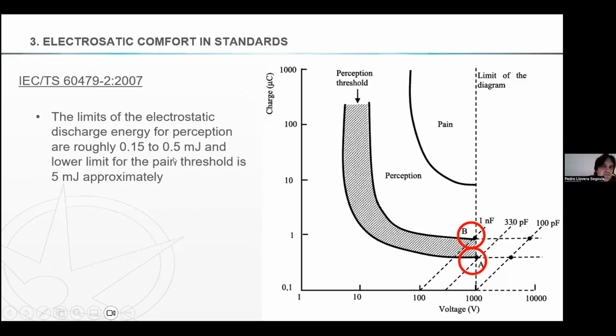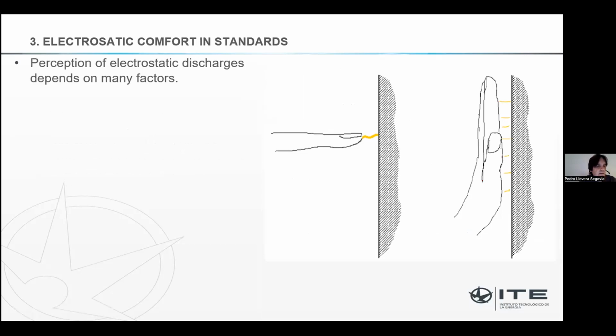From a point of view of energy, the technical specification 60479-2 speaks about 0.15 or 0.5 millijoules for the lower limit of perception, and approximately 5 millijoules for the pain threshold. Perception of discharge depends on many factors. For example, a very simple experiment that does not always work, but in dry conditions can work.